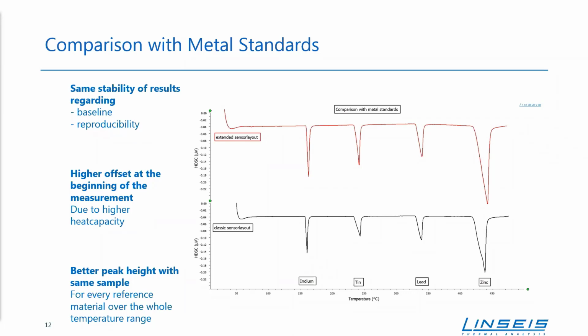But the most important thing in this case is all of our peaks over the whole temperature range are higher. As you can see here, we will compare it for indium directly, but this is what we want to reach, and as you can see, we reached it. The scale, by the way, is the same in both diagrams. So we receive a higher signal here.